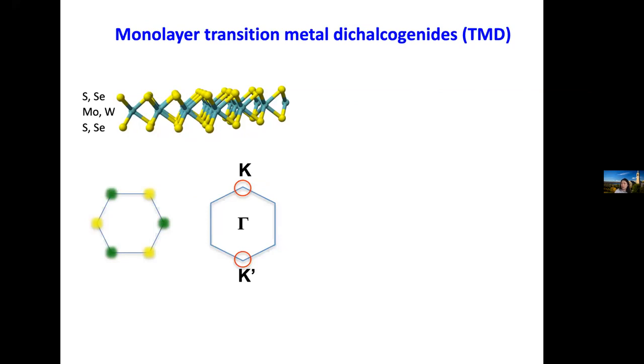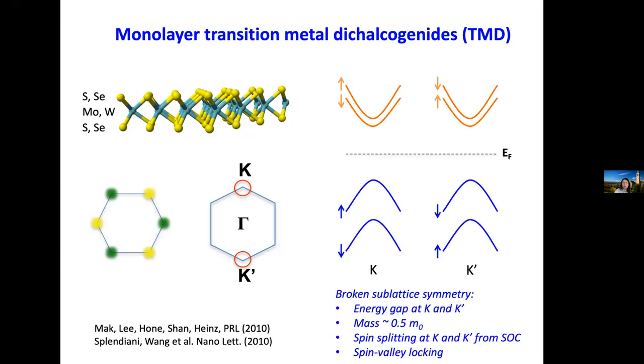So this is a group of layered compounds consisting of transition metal, moly or tungsten, and the chalcogenides in this prismatic structure in the H polytype. So looking down from the top, it forms a honeycomb, just like graphene, but with A and B sublattice symmetry broken. It has been shown by us and colleagues a while back that in the limit of a monolayer, this class of material is a direct bandgap semiconductor with the lowest gap occurring at K and the K prime point of the Brillouin zone. So this separation is on the order of 2 eV.